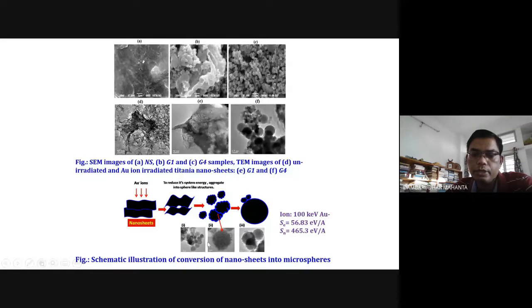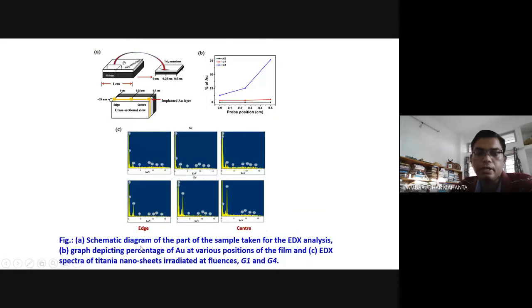Under TEM, we could see very spongy structures, or we can say microspheres. So these seeds can be grown into microspheres. It's a reverse effect that we found in this case, because most of the time radiation-assisted particle growth can be observed, but here a reverse kind of effect was found. Microspheres are generated from nanosheets under radiation.